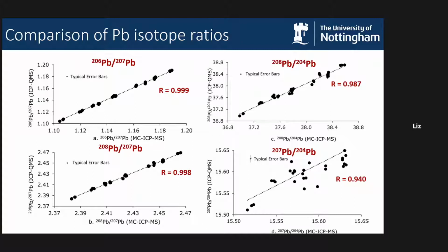And the large difference in isotopic abundance makes for an increased vulnerability to errors in the dead time correction there. And then, of course, the lead 204 signal needs to be corrected for any mercury 204 that might be present. Now, the fact that we digested our samples by hydrofluoric acid reduced that problem with mercury. We were able to optimize for a couple of the other factors. So the dominant and unavoidable factor is the lower counting statistics for lead 204.